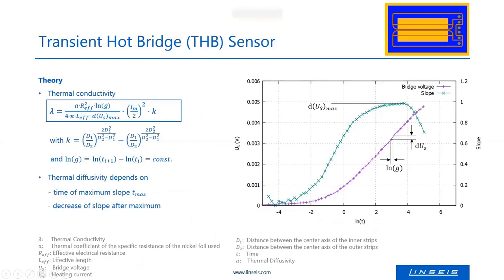The theory looks complicated, but it isn't. This is a typical measurement curve on the right-hand side. The bridge voltage is plotted versus the logarithmic time. At the beginning, at very small times, it takes a little while until the heat is transported through the sensor, until the wires heat up. Then after a while we see the linear increase of the curve. This bridge voltage is directly proportional to the temperature increase. For those who want deeper knowledge, you can look at these equations; we have the original publications in which it is described in more detail.